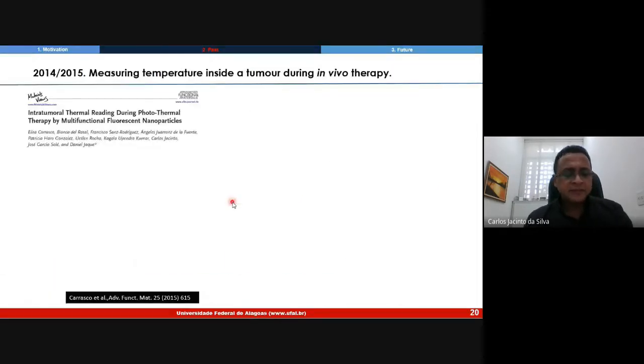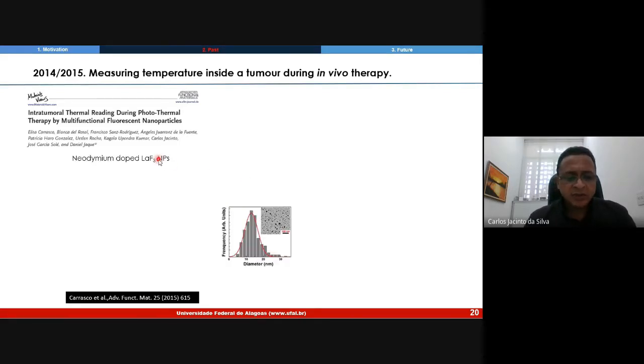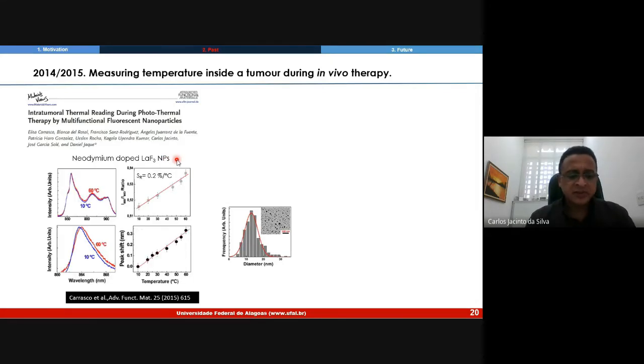In the same way, we demonstrated intratumoral thermal reading during photothermal therapy using neodymium-doped lanthanum fluoride nanoparticles, nanocrystals. This nanomaterial was demonstrated as a potential luminescent nanothermometer and optical nanoheater because the lanthanum fluoride matrix accepts very high neodymium concentration. It's interesting for heating and temperature readout.